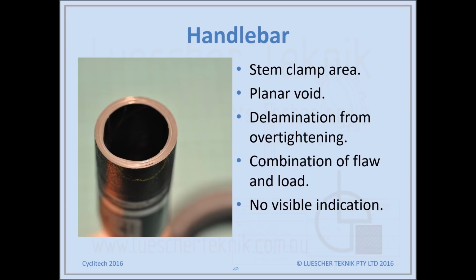Here's another handlebar, and this is the stem clamp area, and you can see a void through here. Now, the area marked in yellow, it's a little bit hard to see on this photo, but it goes from around through like that. So basically this void acts as a delamination initiation point. So then once the part was under load, it was overloaded from over tightening the stem, that void then propagated and created this large delamination.